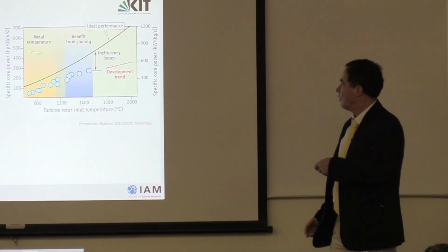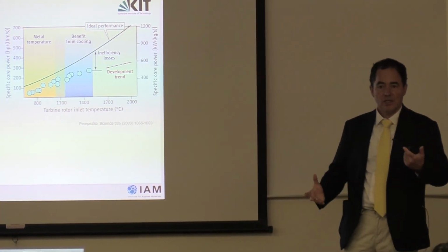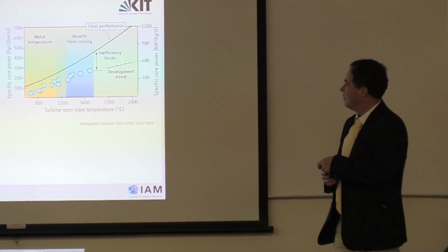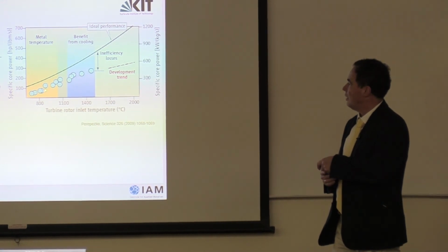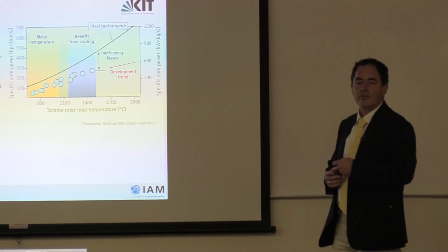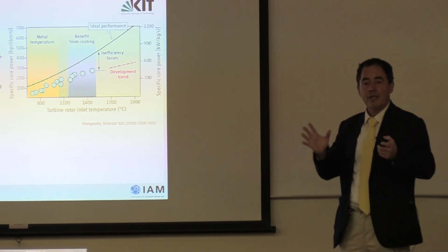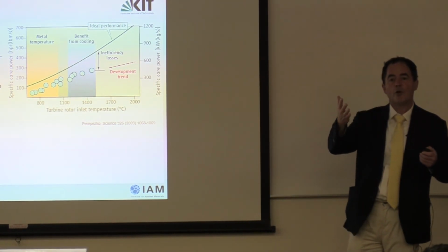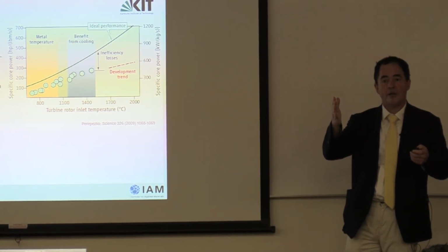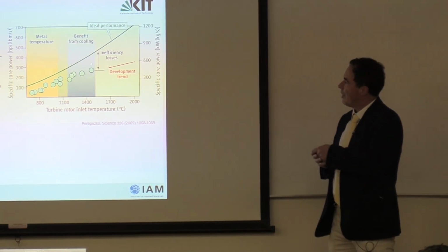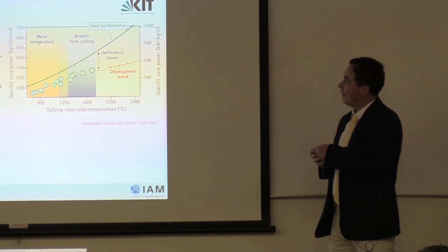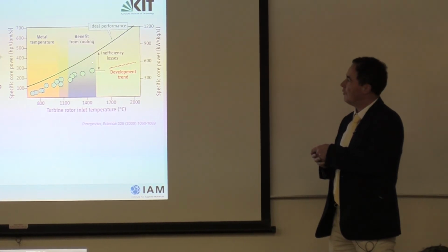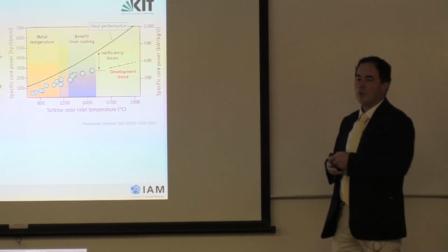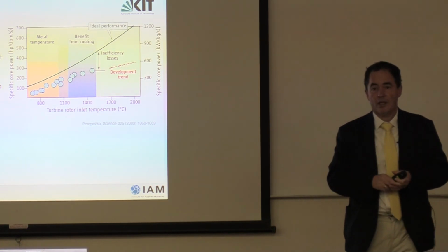That's what I did not show on this slide, but this is the reality. The last uncooled blades were operating here at temperatures below 1100 C. So if we now can use a material which may not need an environmental or thermal barrier coating, we would jump up to about here already. And then if you can go even further, say 100 degrees higher, then you would be here. That would be a tremendous effect on the efficiency.